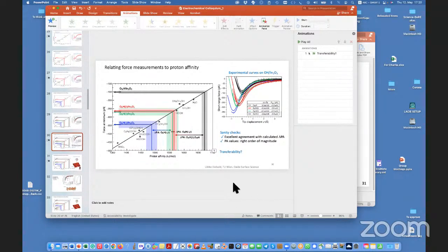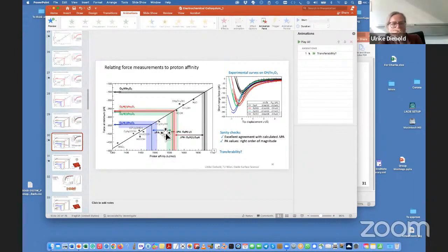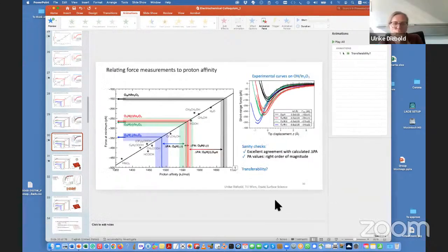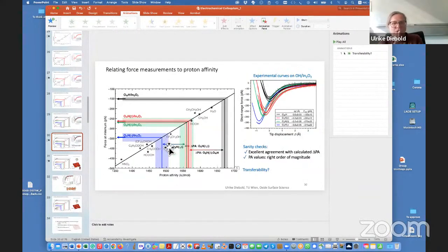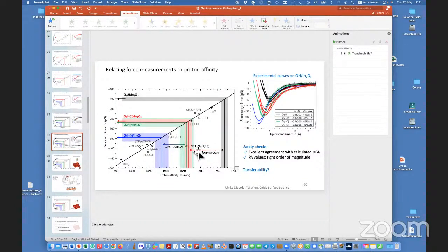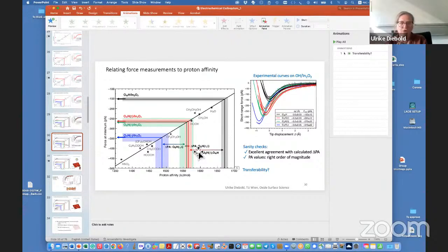Imagine the gamma and beta have different proton affinity. But this is in gas phase, right? These are calculations that Bernd Meyer did. The differences in proton affinity you can calculate quite accurately. You just take your DFT slab, you have your proton on the beta oxygen, and then you put the proton on the gamma oxygen, and you look at the differences in the energetics between the two DFT slabs. So that's what's calculated here.